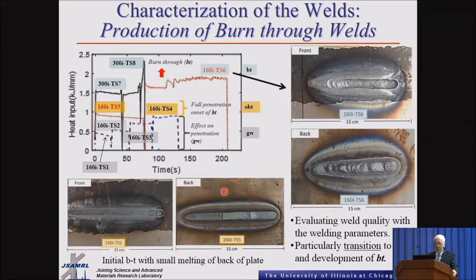Okay, so this is a little crowded, this particular graph in here, but very quickly, in this set of welds in which we have changed, we hold the current constant and we change the travel speed, slow down the travel speed. You can see the increases in heat input, okay? And again, this represents a good weld, as we have said, for this particular case. You see the weld bead well formed. On the back of the plate, you don't see any liquid coming through, okay?